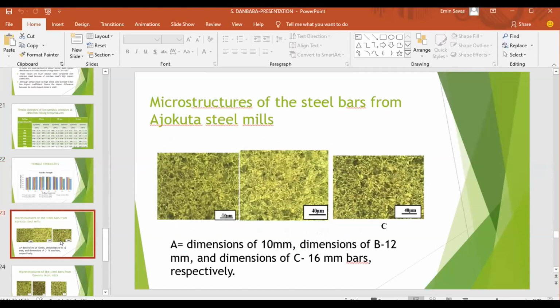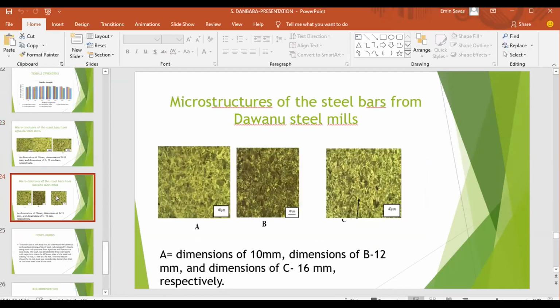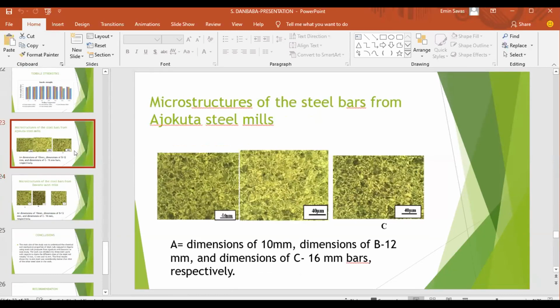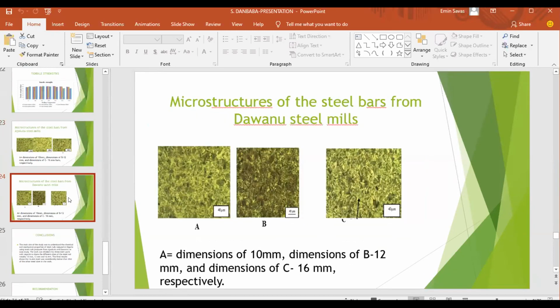We mentioned the microstructural details. It's not very clean here, but the white phase is the ferritic matrix, and the darker phase spread in it is the pearlite of the steel. Again, we have another microstructural view of Dawanu and Ajokuta steels. In the microstructural details, it is difficult to find if there is any difference between them.